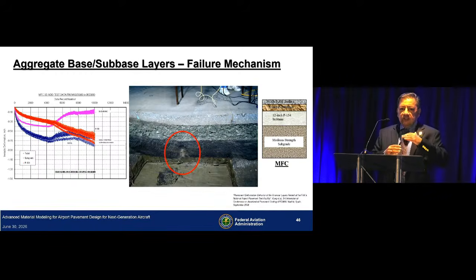So, in pavement structures, when you have these different layers, there's a shear layer that sort of forms at each layer interface, and that's total deterioration of that shear layer, and now you have subbase failure occurring because of significant deformation in the subgrade, and now you have material flow. Why these curves turn upwards is the MDD was not located in the location of maximum rutting. It was not in the center, and it was on the side. So this material flow was pushing the tube of the MDD, and we saw that in the trenches.